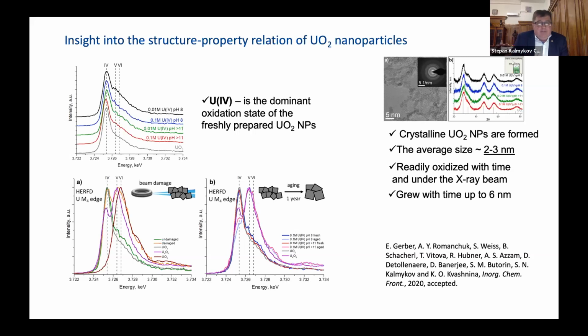But when we have the aging, the first thing we found is that upon aging we have the oxidation of UO2 to U4O9-like particles, with the presence of U(V) and U(VI) in there, and this aging results in an increase of the particle size. So this is not like in the case of plutonium, where we have plutonium nanoparticles that are extremely stable in time. So we have the increase in size, and they are much more sensitive towards the beam damage that we also observe, and we have the oxidation of these nanoparticles under the irradiation.